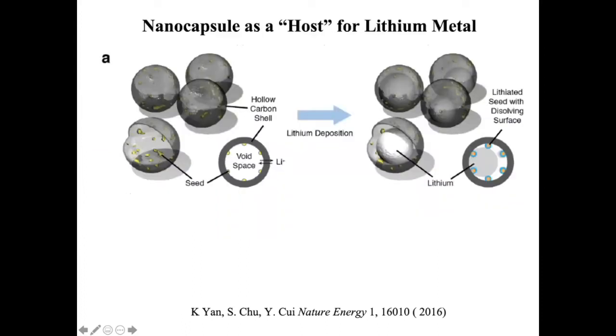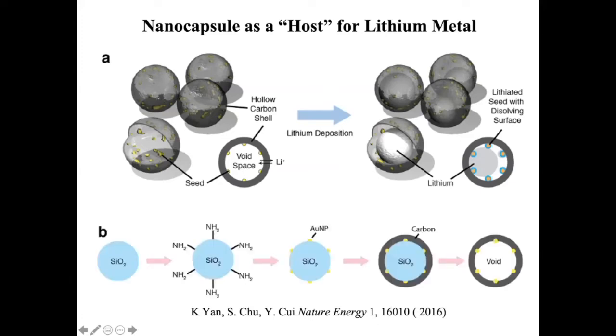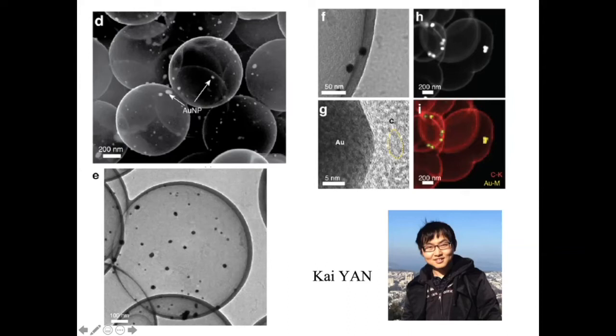So with that, we designed our first host concept of hollow carbon with gold seed in there. Hollow carbon has nucleation barriers. This is a kind of amorphous, slightly graphitic carbon having some conductivity. Lithium can still penetrate through this carbon. And we suspect when you do deposition within certain current density, lithium only likes to nucleate inside this hollow carbon. Then this hollow carbon will be protecting lithium from the outside electrolyte. Certainly the assumption is that this hollow carbon cannot have too big of pores, otherwise electrolyte will wet, go in, and that destroys the purpose. So we made this structure with these gold nanoparticles inside this hollow carbon sphere.